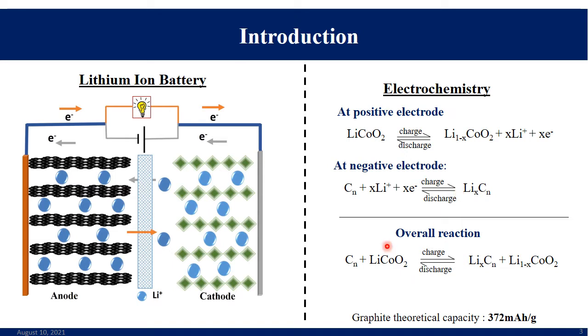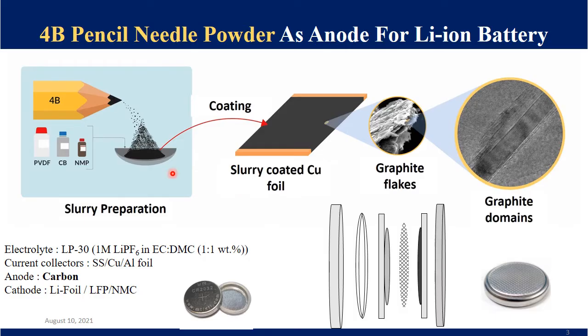In all our commercial batteries, they use graphite as an anode material because of its good dimensional stability. However, it suffers from low specific capacity, which is limited to 372 milliamp hour per gram. So, in this work, we are trying to replace this graphite with a graphite silica composite so that the energy storage capability of the electrodes is improved. So, we propose a facile and scalable process of preparing graphite silica composite electrode from 4B pencil needle powder.